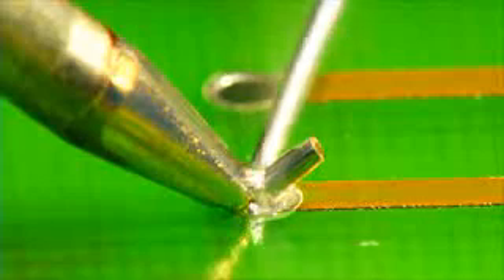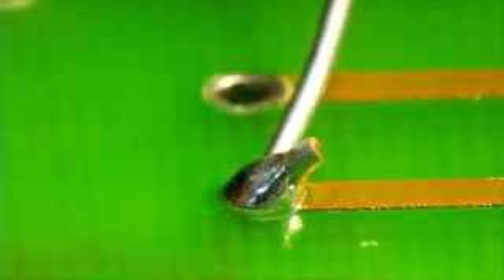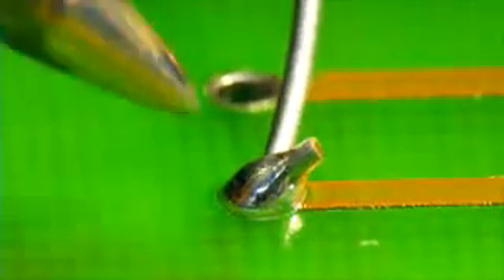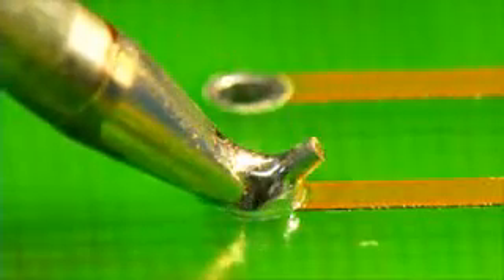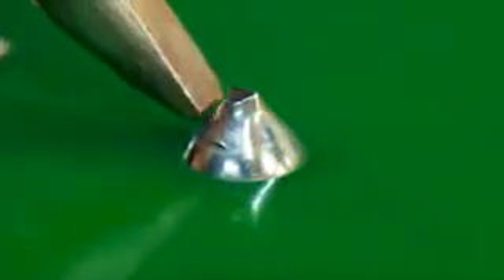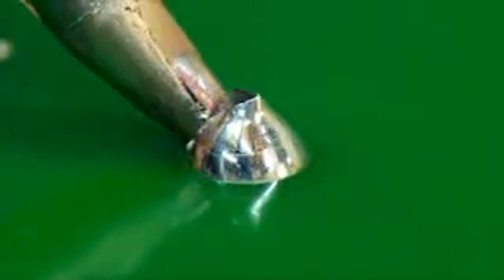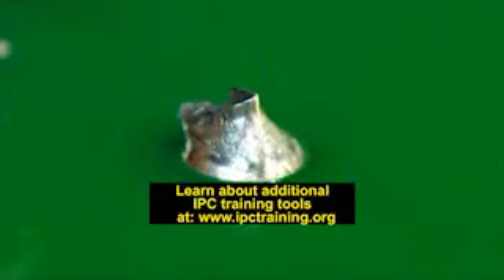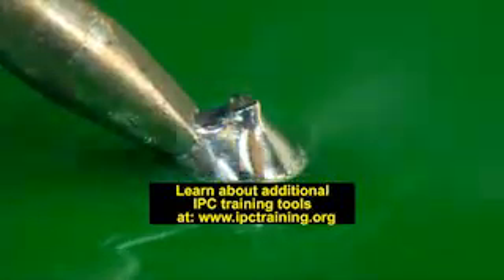This time we remove the tip before the solder wire. Now we'll have to reheat the joint in order to remove the solder wire. Notice what happens when we reheat a tin lead solder joint? It doesn't look as smooth or as shiny as it was before. Now let's see what happens when you reheat the same solder joint using flux. In this case, the solder appears as smooth as it did before.